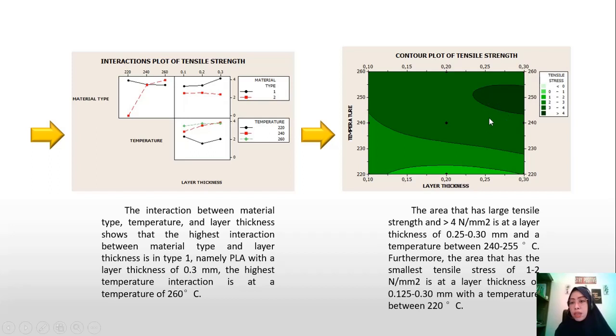You can see in the picture that the area that has large tensile strength, more than 4 Newton per square millimeter, is at this layer thickness and a temperature between 240 and 255 degrees Celsius. Furthermore, the area that has the small tensile stress of 1 to 2 Newton per square millimeter is at a temperature around 220 degrees Celsius. This is the layer thickness.